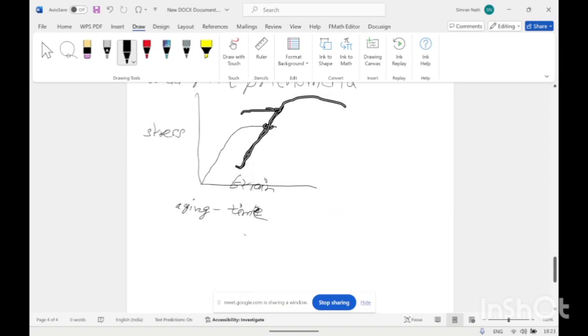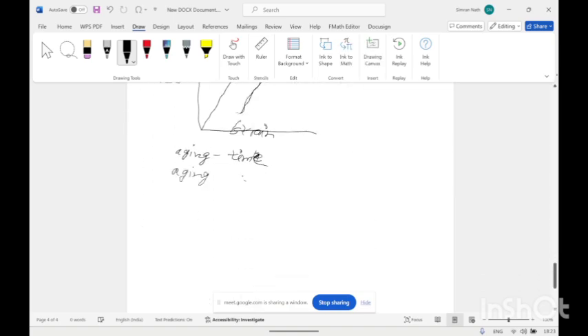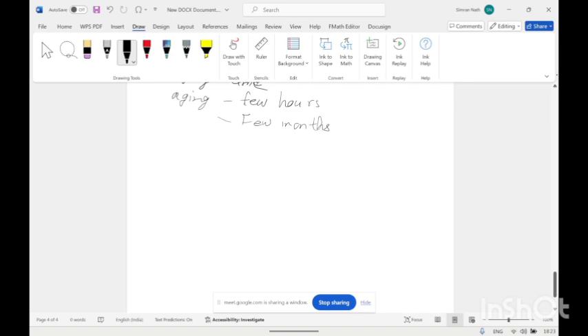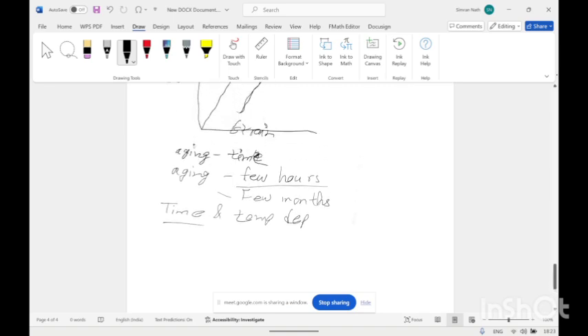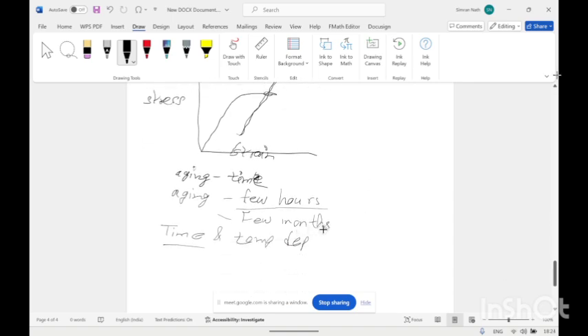So it is also a time dependent process. If aging is only for a few hours, then there will be no difference in the yield strength after reloading. If it is for a few days or few months, then this increase in yield strength is observed. So this is a time and temperature dependent process. For a few hours, there is no significant effect on the stress, but for few months, with increasing time the strain aging will increase.